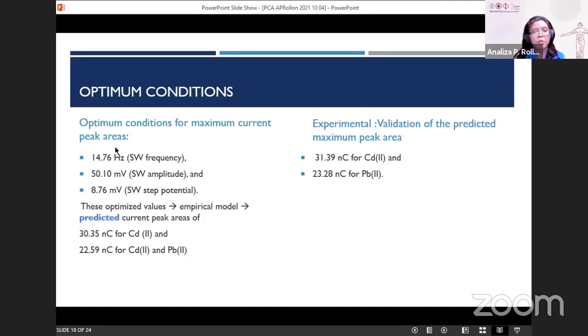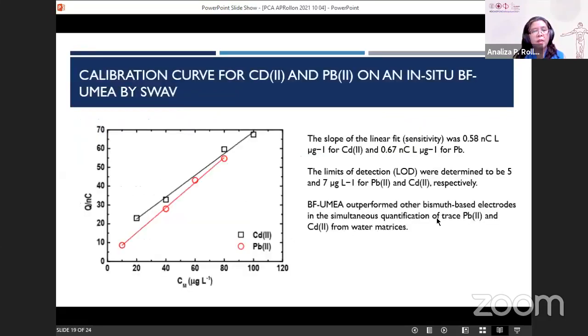And also, if we use this, we are able to determine that the peak area will be 30.35 and 22.59 for cadmium and lead. We validated this and got similar values, very close to the predicted values. And for the calibration curve, the peak area is plotted against the concentration of the two metals, the red one for the lead and the black one for the cadmium.